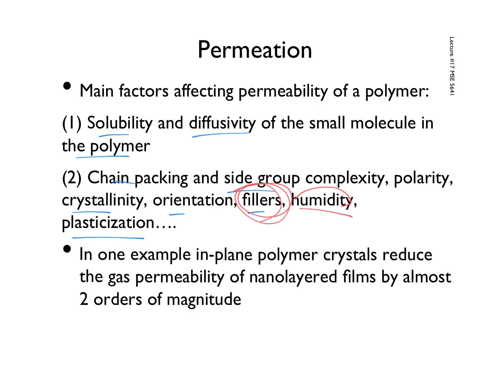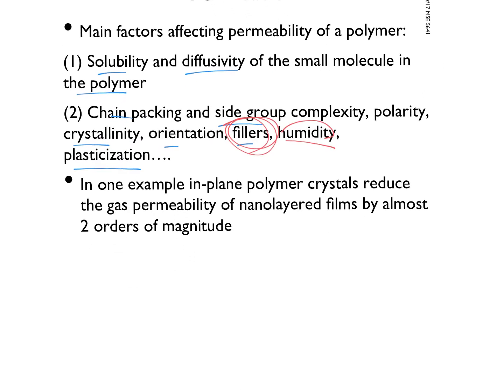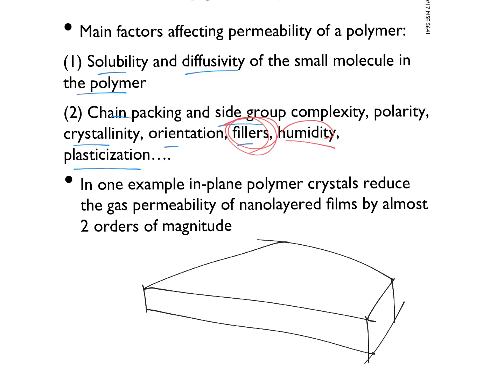One example from the literature: you can take plastic film, and what they were doing was nucleating and growing plastic crystals parallel to the direction of the film. So when it came time for something to diffuse through, it would run into those polymer crystals, and that would help reduce the permeation, reduce the diffusion of pretty much anything, water, CO2, oxygen, through these plastics, by generating polymer crystals that get in the way of that diffusion because it's a more tightly packed structure.